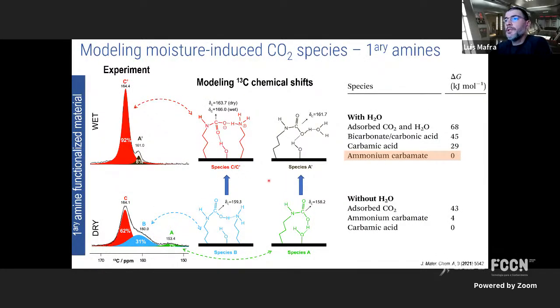And we have computed all this. We have tried to calculate Gibbs energies of all these species. What happened is that the A species, which is isolated, when water approaches these surface amines, it hydrogen bonds like here, and then the peak shifts from 155 or 153 to 161. So it becomes this A prime peak here.